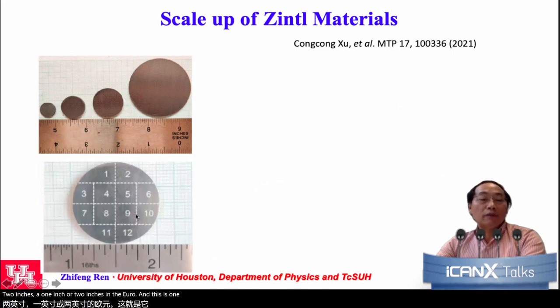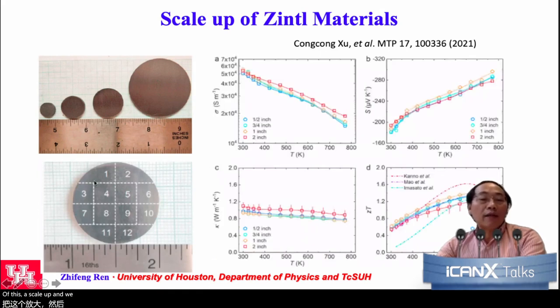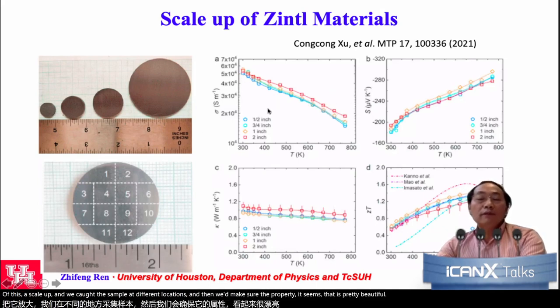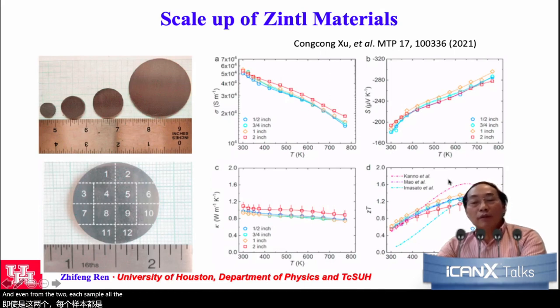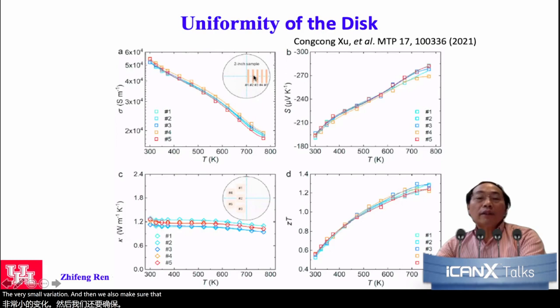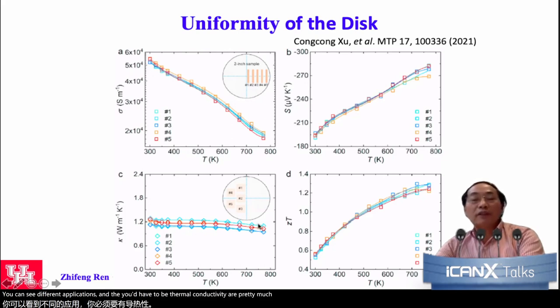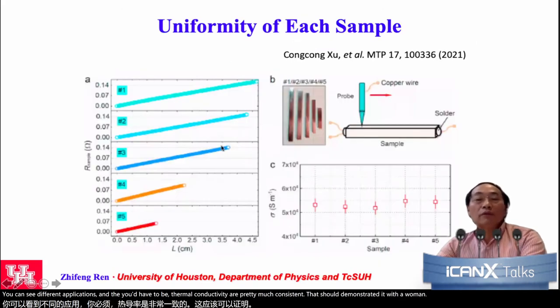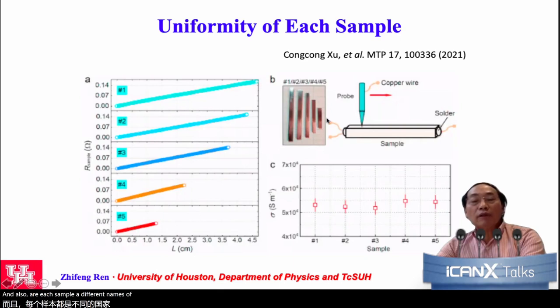This is one of the materials, 1 inch. We studied the uniformity of this scale up, and we cut the sample at different locations and measured the properties. It seems that it's pretty uniform, and even from the 2 inch sample, all the individual properties are pretty much consistent with very small variation. And then we also measured the different regions of the disk for the thermal conductivity, and also the electroconductivity. You can see different locations, and the electroconductivity and thermal conductivity are pretty much consistent. That demonstrates the uniformity. And also for each sample, different lengths from different locations, they are very much linear. That means they are very uniform.